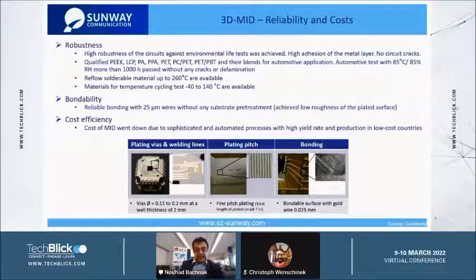So bondability is very interesting if you want to use it for 3D packaging, because this laser structuring makes the surface a little bit rough. And the roughness of the surface with normal, I would say, laser structuring LDS is about 20, 30 micron. And the wire, if you use a 25 micron wire, the diameter of the wire is smaller than the roughness. And if you have wedge bonding, for example, you will cut the wire before you bond it because of the high roughness. And here we have developed surfaces where we have lower than 10 microns, so lower than the radius of the bonding wire. We don't need any pre-treatment for that. It's done from the beginning. So it's a combination of laser structuring and plating where we can achieve such roughnesses where we don't need any pre-treatment for the surface.